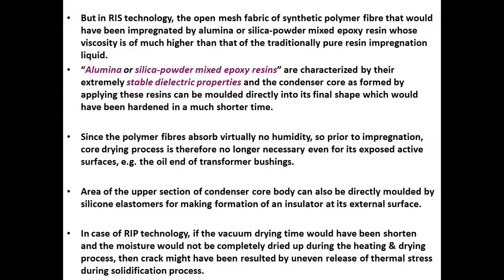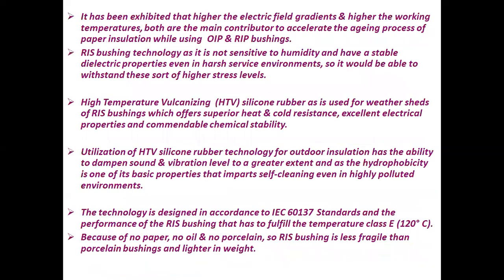In case of RIP, that is resin impregnated paper technology, if the vacuum drying time is shortened and the moisture is not completely dried up during the heating and drying process, then cracks might result from uneven release of thermal stress during the solidification process. This is the disadvantage of using RIP technology. It has been exhibited that higher electric field gradients and higher working temperatures are both main contributors to accelerating the aging process of paper insulation in oil impregnated paper and resin impregnated paper bushings.